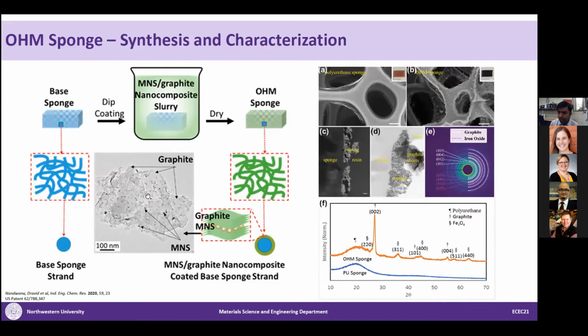This is the transmission electron microscope, TEM, graph, and you can see the composite has a layered structure of graphitic carbon as well as magnetic nanostructures, and that coating basically makes the sponge more functional. So here on the right side you see the characterization plot. Figures A and B are scanning electron microscope images, where figure A is just a blank polyurethane sponge, and figure B is the coated sponge, where you can see a very thin coating of a nanocomposite. Figures C and D are cross-section transmission electron microscope images, where the coating can be seen. The approximate thickness of this coating is less than a micron, and just this thin coating changes the overall function of the sponge.